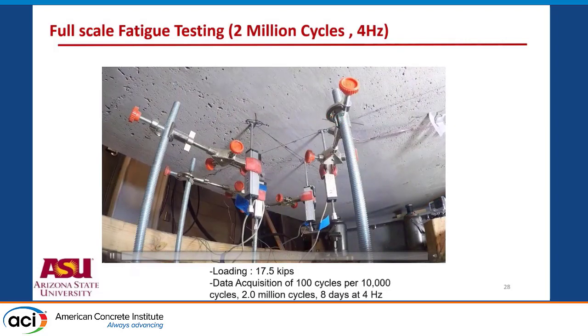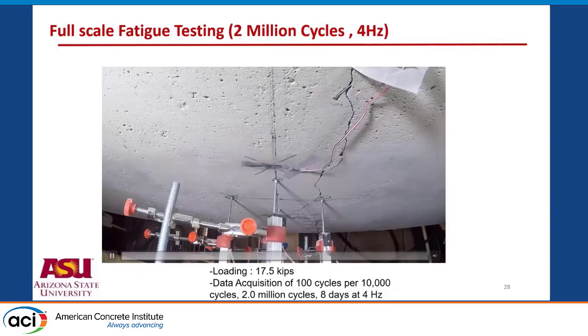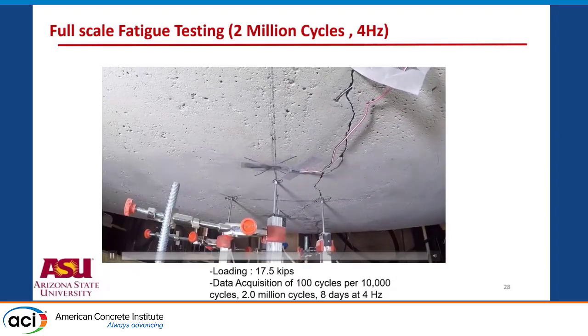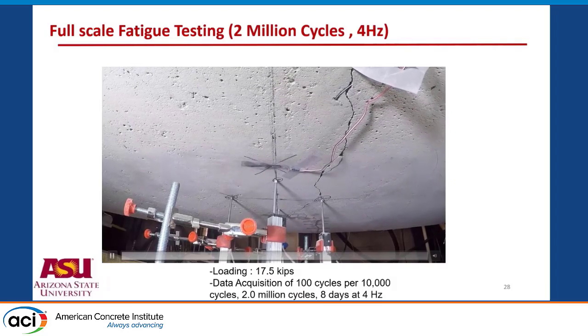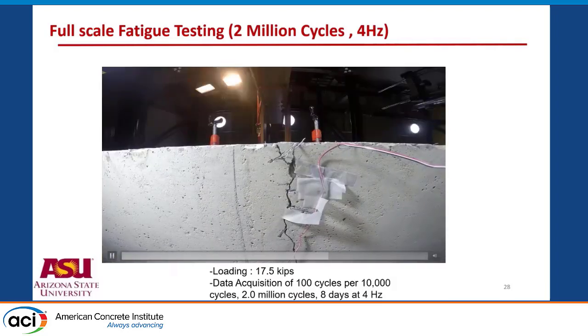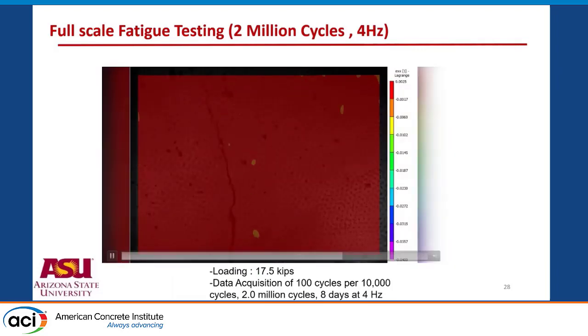And this is underneath, again with the GoPro capturing the deformation. We're exercising this existing crack that we put in there, and then we can do the data acquisition and measure the cyclic response and the opening of the sample at the end. This is the DIC done on the fatigue test. You can see how the crack is being exercised, opening and closing 4 times a second. This is a slow motion of the fatigue test, maybe about 4 seconds within the entire 8 days being shown here.